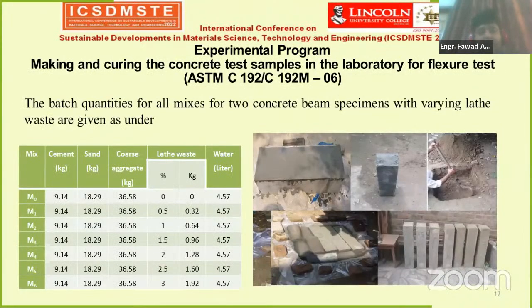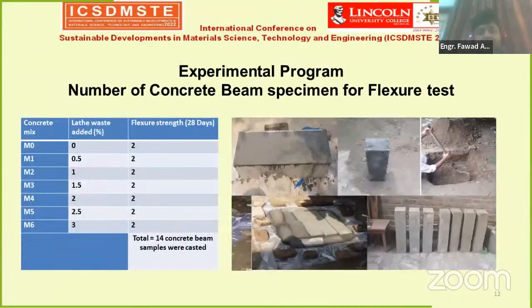Now for beam specimens, I casted 2 concrete beam specimens for each companion mix. We have 7 types of mix: M0, M1, M2, M3, M4, M5, M6. These are only the designations. The lathe waste addition is 0, 0.5%, 1, 1.5, 2, 2.5, and 3. And the flexure test was only performed at 28 days.